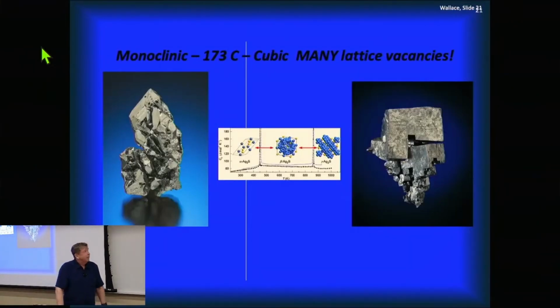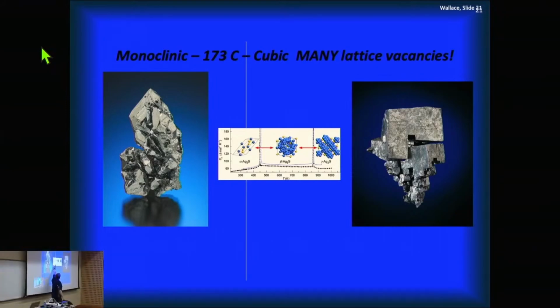So this is kind of an attempt to show, basically, in this case, a high temperature, or I'm sorry, a low temperature acanthite, so the monoclinic structure. We show a monoclinic structure here. So silver is the blue, the interaction with the sulfur is the yellow. Then we're going to go through a phase change, and this is, unfortunately, in Kelvin, and nobody uses Kelvin, but